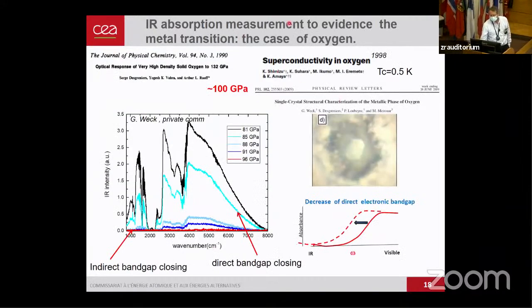So now the infrared absorption measurements. First, to convince you that infrared measurements are a signature of the change of electronic state from insulating to conducting to metallic phase. This is a measurement that has been done on oxygen. Oxygen is a molecular solid that also metallizes around 100 GPa, which is easier. It has been characterized by optical measurements, by electrical measurements, even measuring the superconductivity. At the ESRF some years ago, we measured the structural change at the insulator-metal transition.